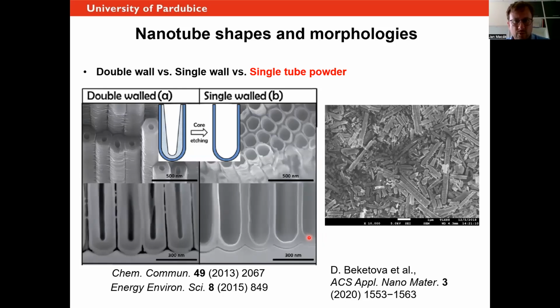And these tubes, when you're looking very carefully, usually have inside, especially at the bottom part, some porous layer inside. You know? It has been overlooked for a while, but then people found out, and then it created some attention. And actually, it turned out that this inner porous wall is TiO2, which has lots of carbon. So it's basically contamination from the electrolyte. And if you do etching, you can actually remove it, and the rather pure TiO2 stays there